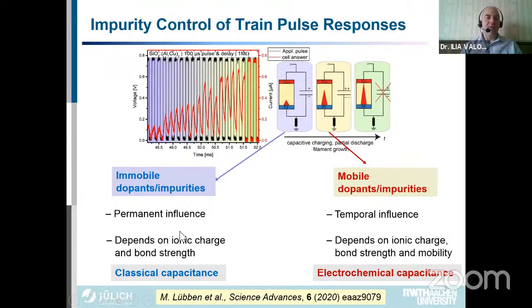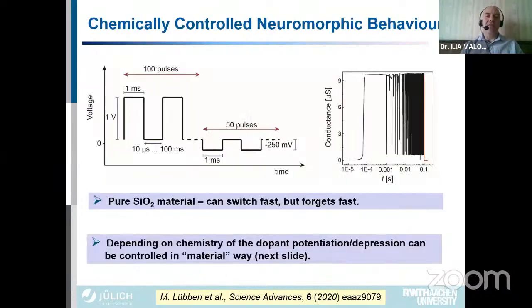So the initial phase is controlled by the immobile dopants or impurities. Their permanent influence depends on the ionic charge and bond strength. It's the classical capacitance. We have electrochemical capacitance as an additional component, which is determined by the mobile dopants. It's a temporal influence. It can be changed with time, and depends on the charge, bond strength and mobility. Using these two effects in addition to the electromotive force and applied external voltage, you can better control your neuromorphic device. It's only a demonstration, the last two slides, of how it works.